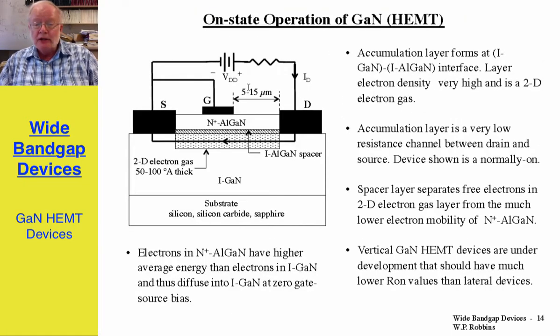The on-state operation of the device occurs when you have zero gate to source voltage, because this is a normally on device. In that situation, the electrons which are in the N+ aluminum gallium nitride near the interface are able to diffuse across and into the intrinsic gallium nitride. And the reason for that is the average energy of the electrons in the N+ aluminum gallium nitride is higher than that in the gallium nitride layer, and so they just naturally will diffuse across.